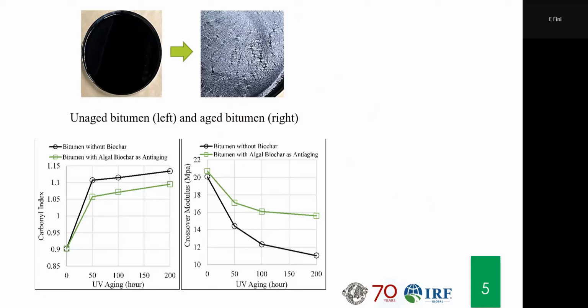You can see at the beginning, the crossover modulus of the sample, the aged one, is up there at 20 megapascal. As it ages, the crossover modulus starts dropping, initially much more, and then it slows down, but it still keeps going down. Here in this figure, there are two different patterns. You can see black and green. One has anti-aging, one doesn't have anti-aging. We'll talk about it in a minute.